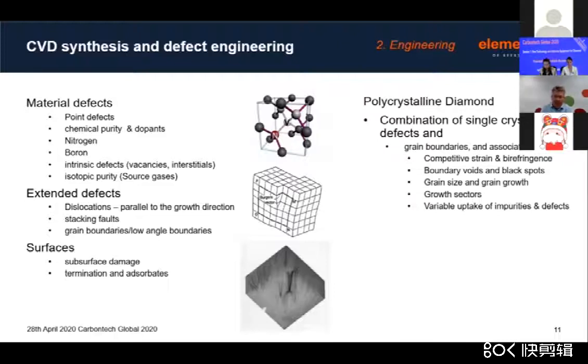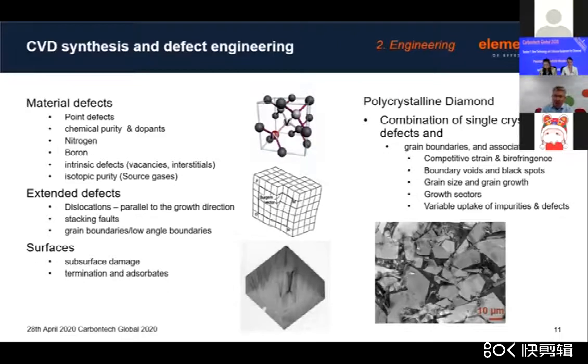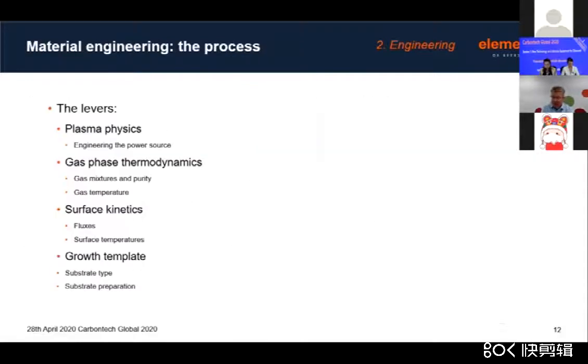And finally, polycrystalline diamond combines all of these difficulties along with the complexity of grain boundaries. You can see a lot of different types of extended defect, particularly in diamond, as well as all the point and extended defects that you'd find in single crystal diamond. So in this picture of the material, you've got different growth sectors, different uptake of impurities, stacking faults and grain boundaries and strain and voids and many other complexities. So polycrystalline diamond, in a way, is a much more complicated material to think about in some respects.